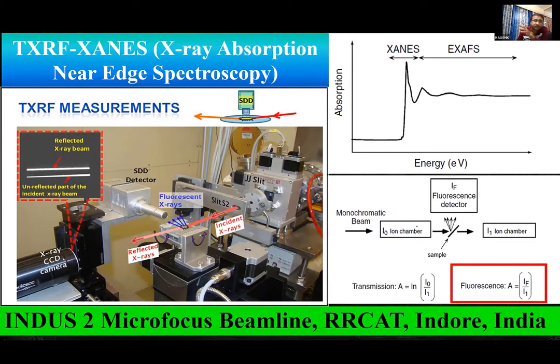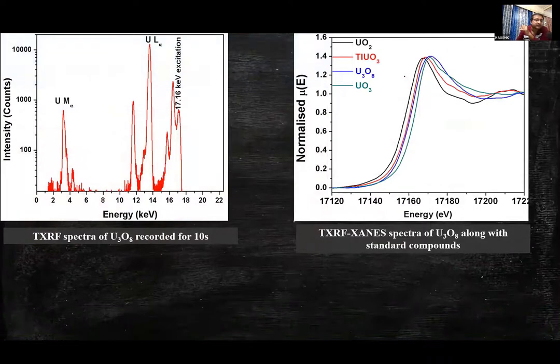We have used two ionization chambers, and the XANES measurement can be carried out in two modes: the transmission mode and the fluorescence mode. We used the fluorescence mode for the speciation study. In XANES measurement, we are basically interested in the region of plus or minus 50 eV around the edge position. This is the TXRF spectrum of U3O8 recorded for 10 seconds. Only 10 seconds is sufficient to give a very good count for uranium L alpha, which is chosen as the region of interest, or ROI.